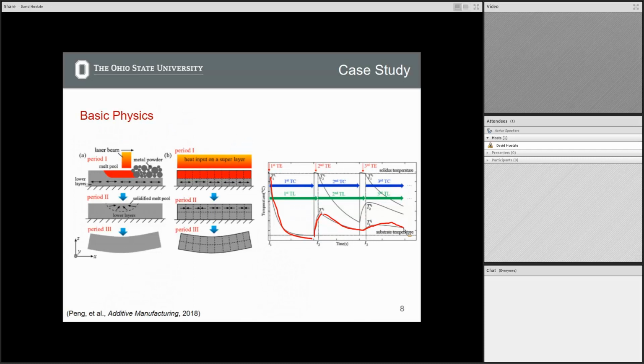Okay. The act of freezing in the material locks the material into some sort of configuration. And so if I wanted to understand what is the accumulation of stress in the part, I can look at these individual time indices in which the material locks into place at the top layer, and I can just start to stack up all these individual layers that are being held into these different configurations in terms of the thermal expansion and contraction. That is the main idea here. Same thing happens with layer 2. It heats up to the melting point, goes down, and then it goes into this profile, and the next layer goes down.